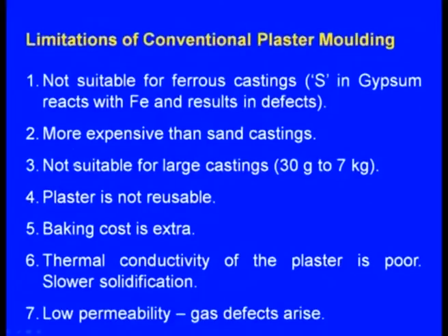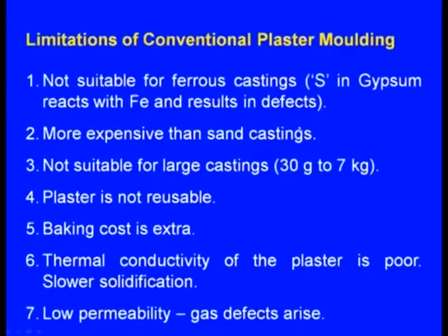Now, what are the limitations of the conventional molding process? Not suitable for ferrous castings. The sulfur in gypsum reacts with iron and results in defects. So, this gypsum contains sulfur. So, because of that there will be some defects. So, not suitable for making ferrous castings.